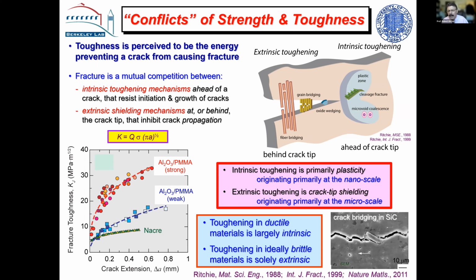And there you have to operate what I call extrinsic mechanisms. These operate primarily behind the crack tip or at the crack tip. And they are associated not necessarily with plasticity, although plasticity could play a role. They're associated with shielding. They are mechanisms that basically shield the crack tip from the applied stresses. And they carry load, basically, these mechanisms, which would otherwise be used to propagate the crack. And the classic ones are, of course, bridging. You have bridges across the crack, they sustain load.